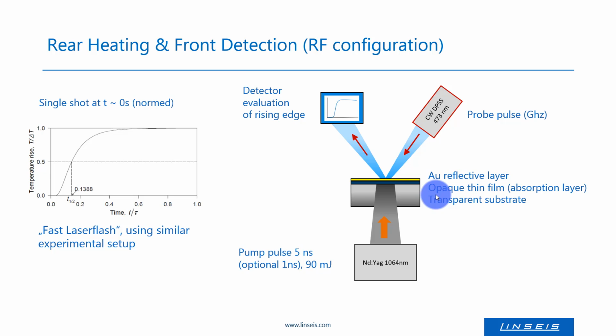In order to detect the local change in temperature, we need a transducing layer, which needs to match with the wavelength of the detection laser. In our case, we either use 473 nanometer in combination with gold, or 785 nanometer in combination with aluminium or platinum. These are the two most commonly used wavelengths.